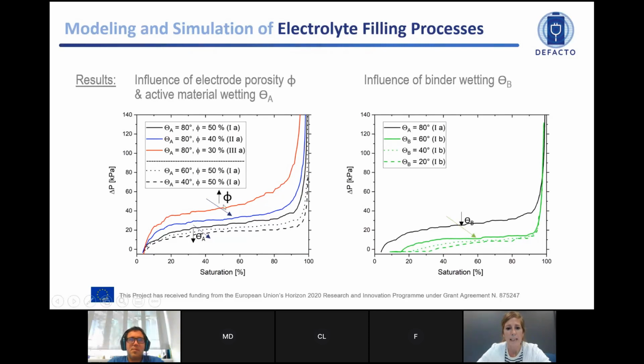Basically here, what you can see is that when we increase the porosity, the pressure gradient goes lower, so it facilitates the penetration, and we can even reach a higher saturation percentage. In the same way, if we reduce the contact angle, or let's say we improve the wetting behavior, we obtain a similar outcome: we reduce the pressure gradient between the two flows, and then we achieve higher saturation values. We have also taken into account the binder wetting parameter on the contact angle of this binder. And here what you can see is that by reducing this contact angle, we can certainly reduce the pressure gradient, but there is also a certain shift from zero, where you can reach a higher saturation without any pressure. And then again, we reach a similar saturation percentage.